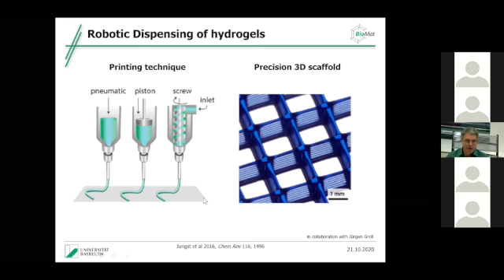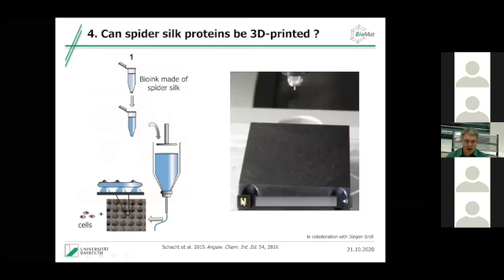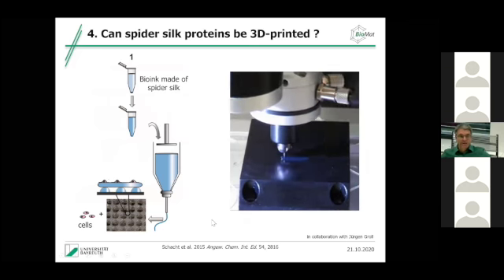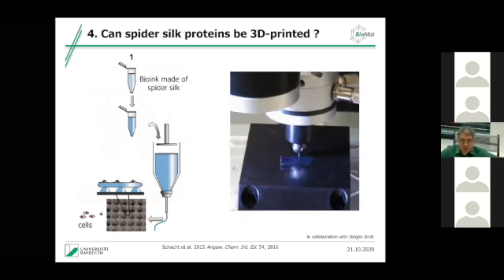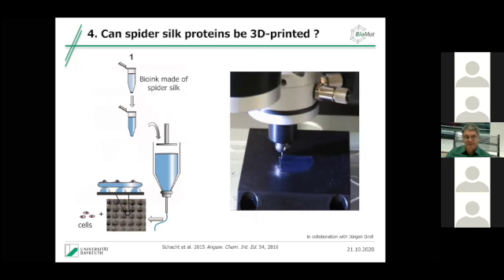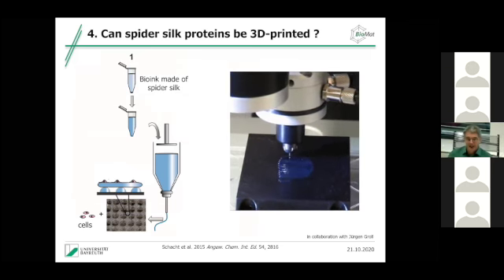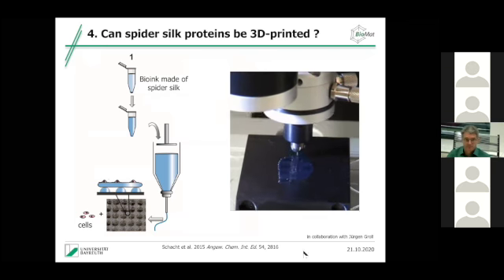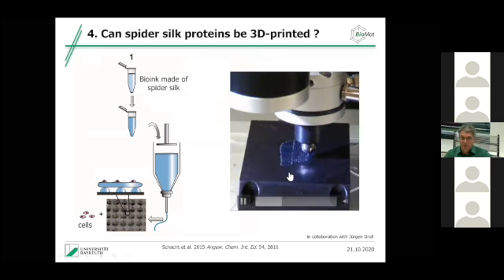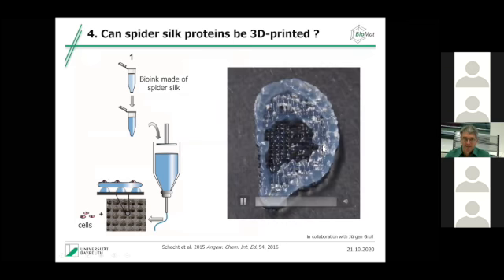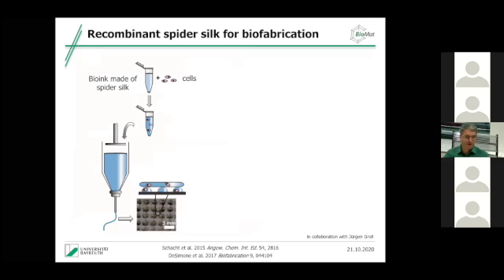Okay, so can we do that with spider silk? This was the first test, and you see here a 3D printing in real time. You see it immediately hardens as soon as it leaves the needle, and you immediately can start with the next layer. And the first idea was, well, now we 3D print the stuff, and here we 3D printed something that looks like an ear, 64 layers, and then we inoculated cells on top. The drawback of that system is, and this is for all kinds of tissue engineering approaches, that the cells have to go into the scaffold and find the places.